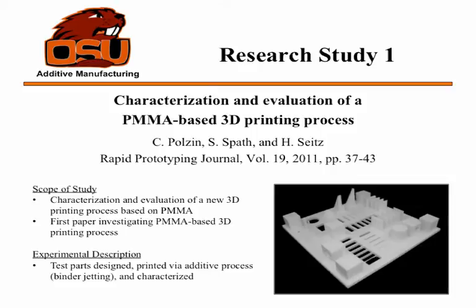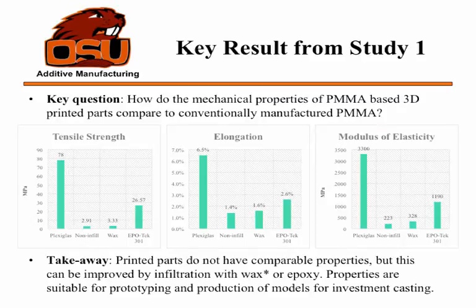All right, so the first research study I looked at evaluated this binder jetting process. They created this part, as you can see on the right, and evaluated it based on different process parameters. Basically they asked, how do the mechanical properties compare to conventionally manufactured PMMA or plexiglass? As you can see, plexiglass outperforms most additively manufactured PMMA, but wax infills and epoxy, which is on the left there, really improve the properties overall.